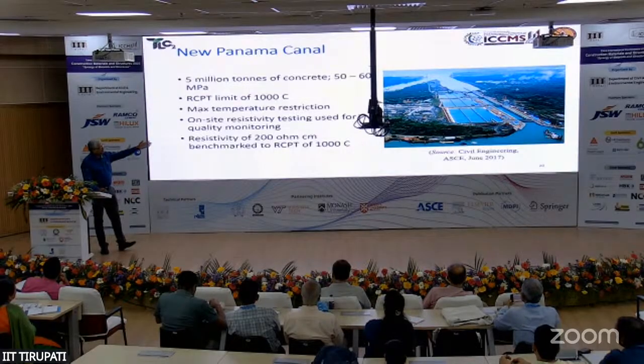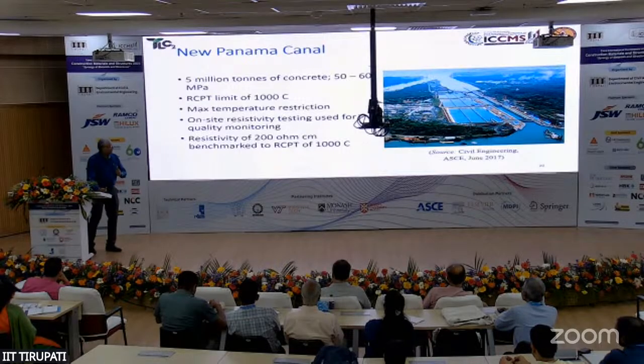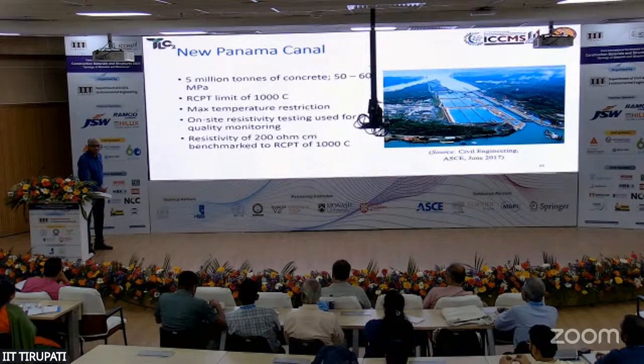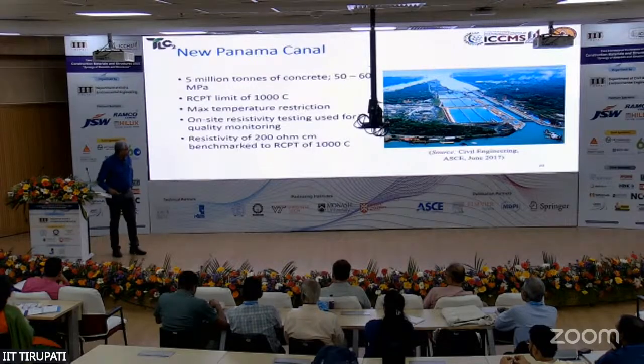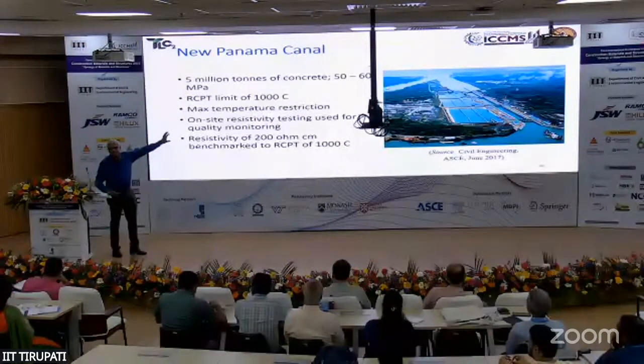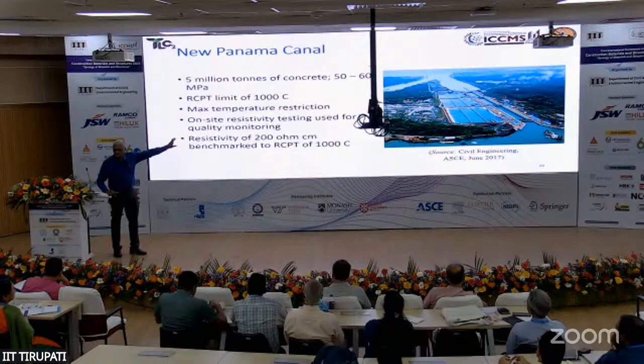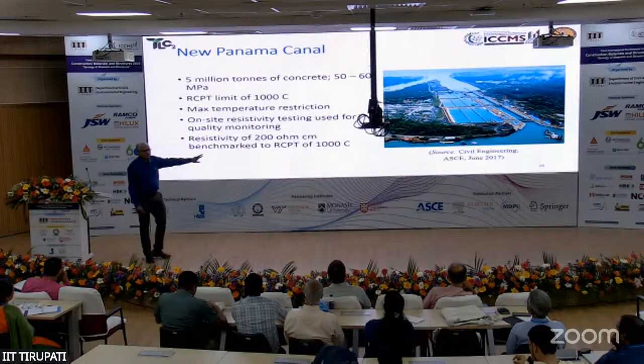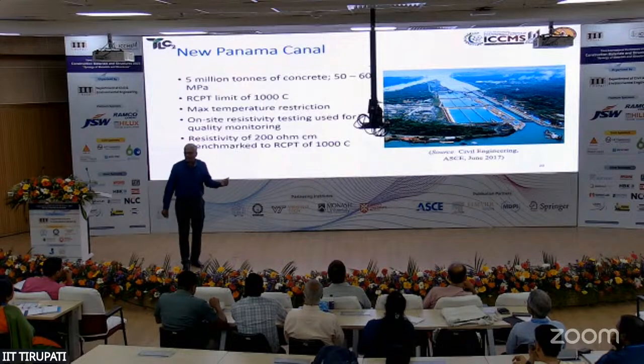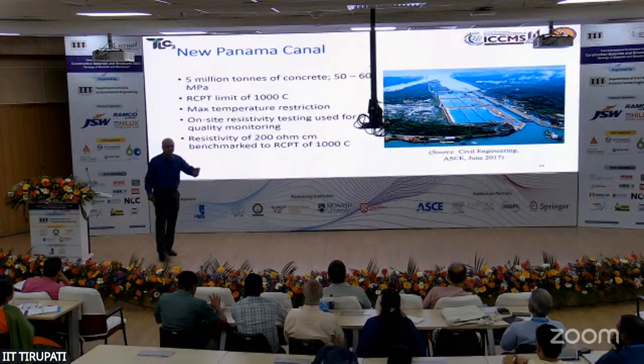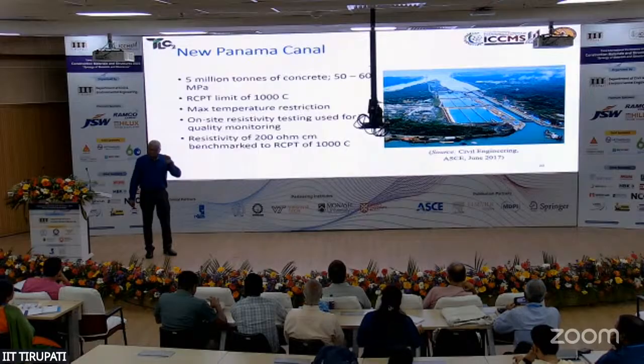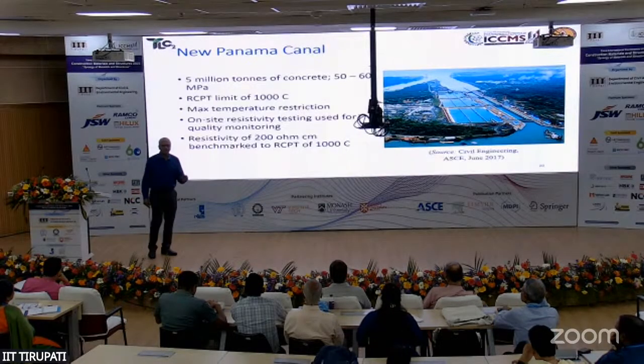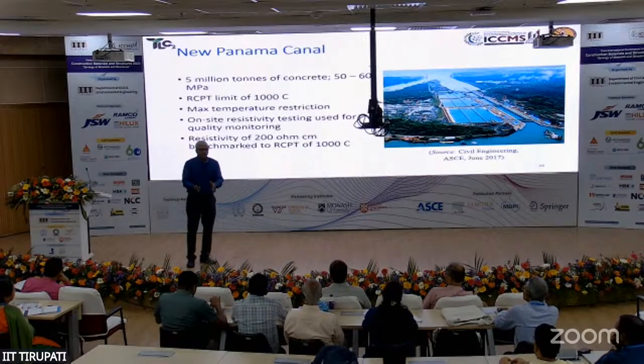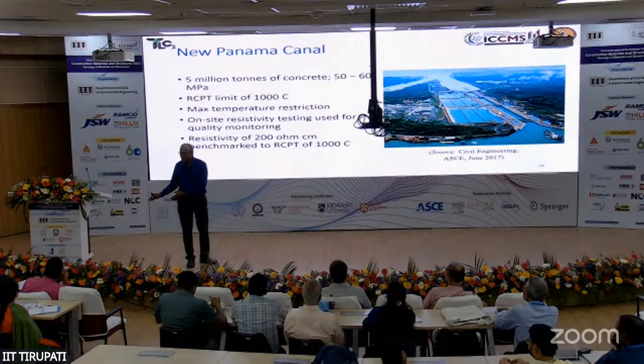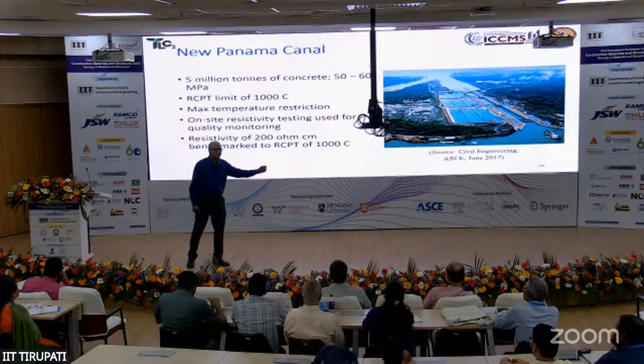Now here, a performance spec example is the new Panama Canal, which was looked at to determine what would be the control of the concrete quality on site. So here what they did was they established the concrete quality that is needed in the lab as 1,000 coulombs of rapid chloride penetration. And they correlated that with a field-based test, that is the resistivity measurement. And they found that for a certain level of chloride penetration, this is the resistivity that I want to have in the system. They use the resistivity to actually measure the parameter directly on the constructed elements. So look at this. We don't have to rely anymore on lab specimens. We are actually measuring directly the durability on the site.